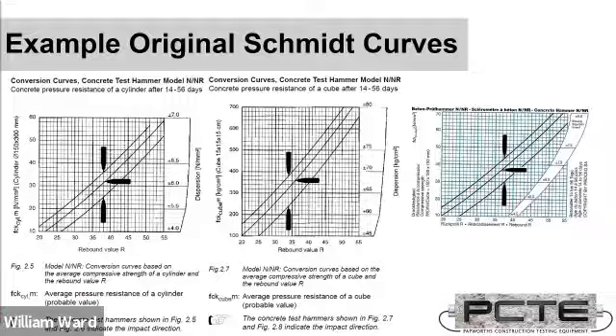A particular one I want to call out, the curve printed on the side of the Schmidt hammer, that's the green curve on the right-hand side, may be a cube curve. So if you have your new original Schmidt purely mechanical hammer and you use the curve on the side as your main measurement of strength, you may be overestimating your concrete strength. You need to be mindful of what that manufacturer conversion curve is. One other point with these curves is they're most commonly created using a standard Portland cement concrete. So if your concrete has a different construction, a geopolymer concrete, say, it may be inappropriate to use the manufacturer's curves. One of the other ones that comes up quite a bit is cement testing. If you're testing cement, the curves were built for concrete. If you want a cement curve, you will need to build that yourself or make use of one in literature.